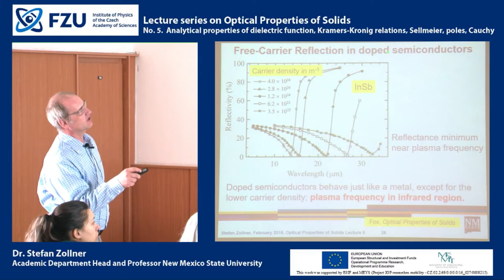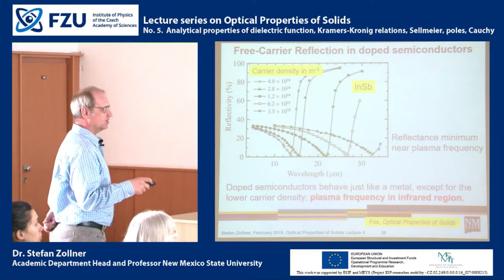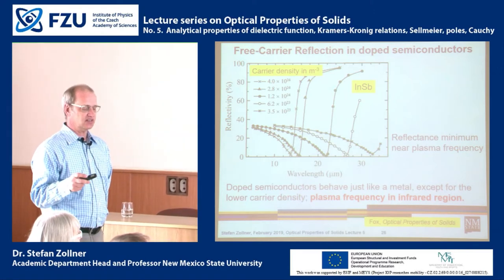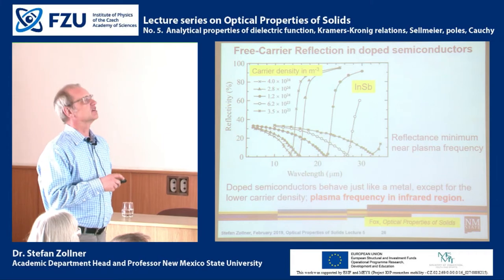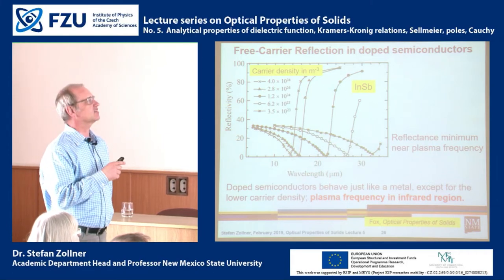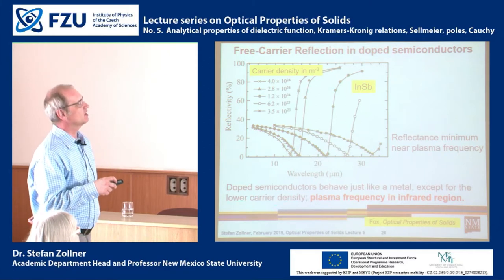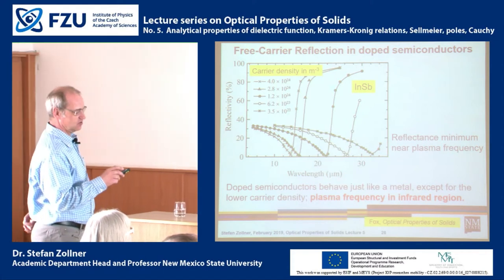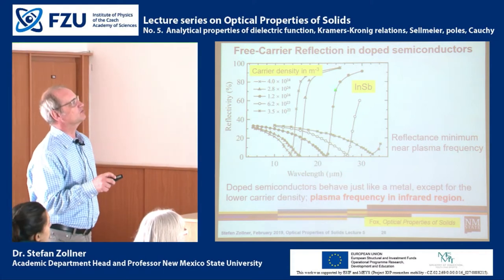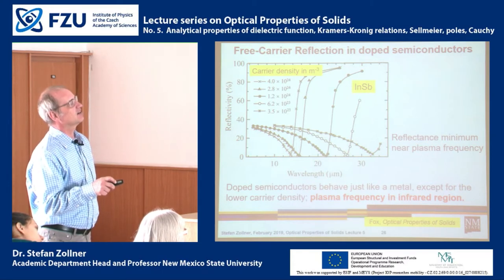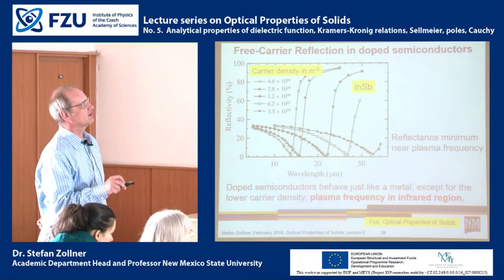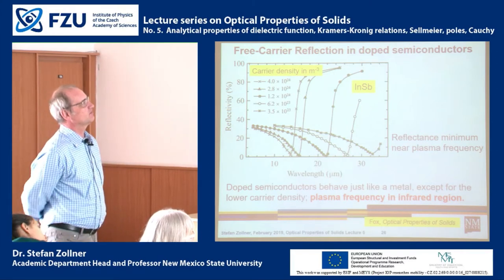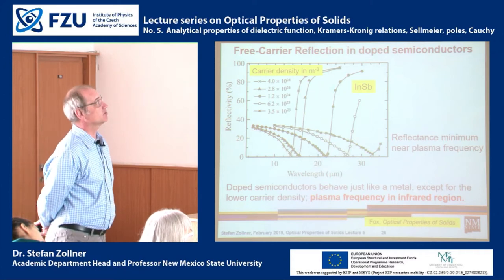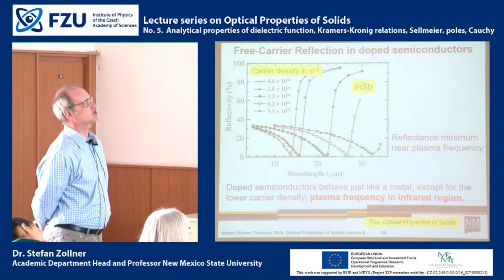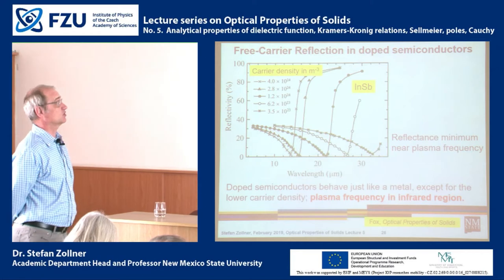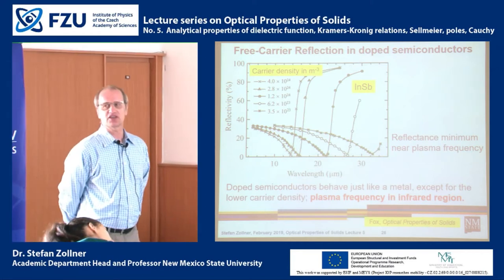And you see here a very nice drop at the plasma frequency. But the plasma frequency in a doped semiconductor is in the infrared region, not in the ultraviolet. There are two reasons for that, and one of them is the low carrier density. There's another reason, and that has to do with the effective mass, and I'll get to that later. So in doped semiconductors, just like in metals, we see a minimum in the reflectance near the plasma frequency. And in this case, because the interband transitions are at much, much higher energies, the interband transitions don't get in the way. And therefore, we can observe the Drude model actually much better in doped semiconductors than in a metal.